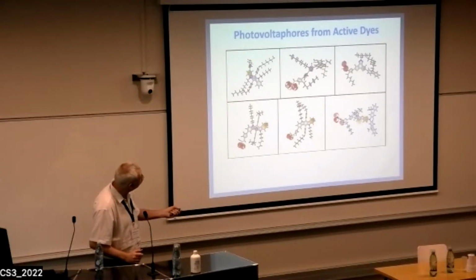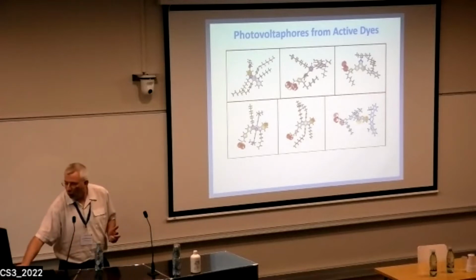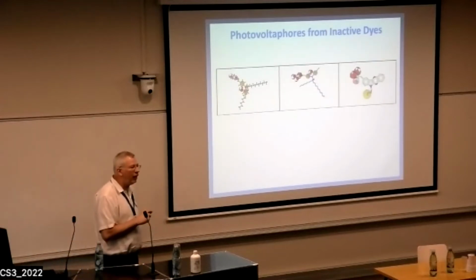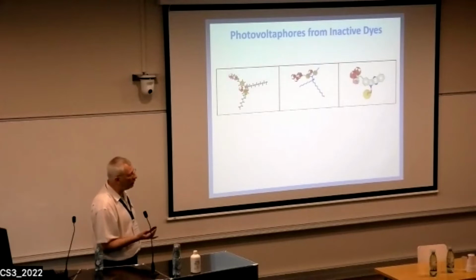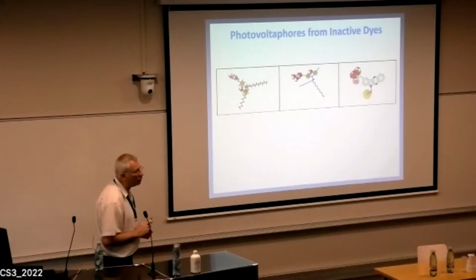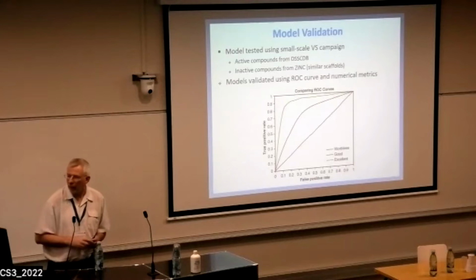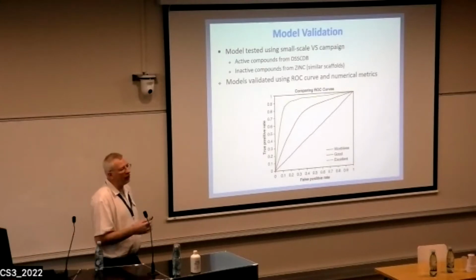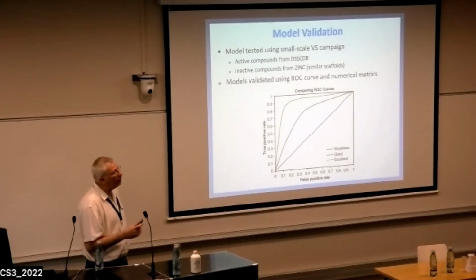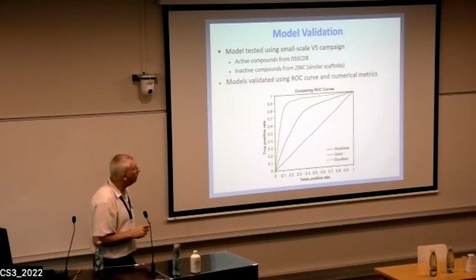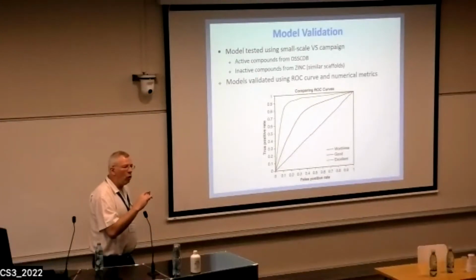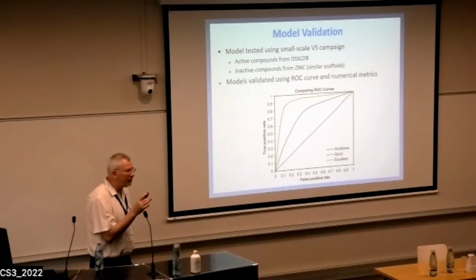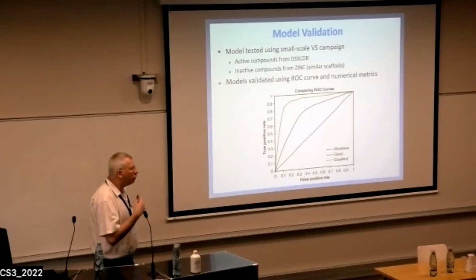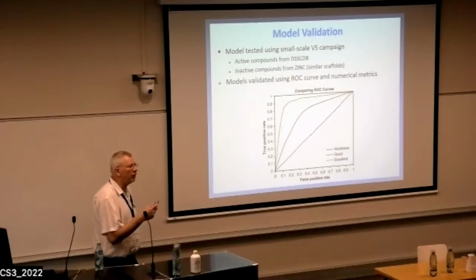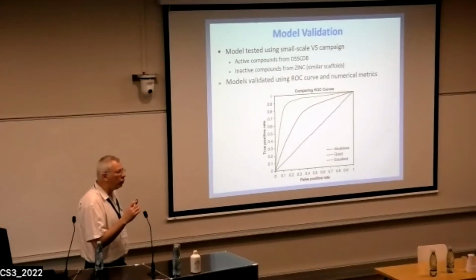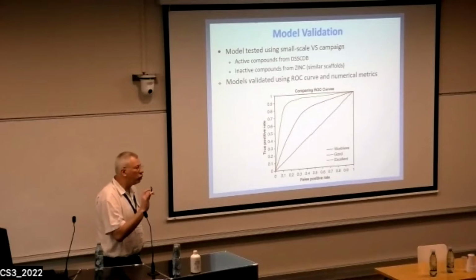Each one is superposed on one of the dyes. We also generated models for the inactive dyes. So in order to filter the false positives, this is some of the models of the inactive dyes. We validated the model using small-scale virtual screening, basically taking the active dyes from the database, augmenting them with similar compounds from ZINC with the same scaffold, did the virtual screening, calculated the ROC curves, calculated some metrics, and eventually we focused on 18 models which looked to us good.